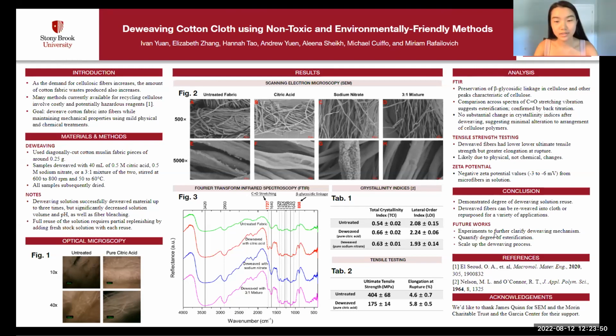We found that the deweaving solution was successfully reused 3 times, but significant decreases in solution volume, pH, and fiber bleaching were observed. Thus, the solution should be replenished with fresh stock solution during each reuse. Next, as seen in Figure 1, optical microscopy showed loosening of threads, disappearance of the weave pattern, and removal of contaminants after deweaving.